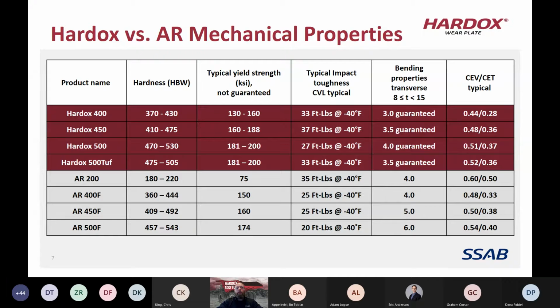Generally, people use this more when they're actually forming the product instead of just using it in the flat plate forming. But with Hardox, we guarantee better bending properties. So our bend radiuses are much tighter with Hardox than you find with standard AR, and we actually have a guarantee for the bend radius for Hardox.